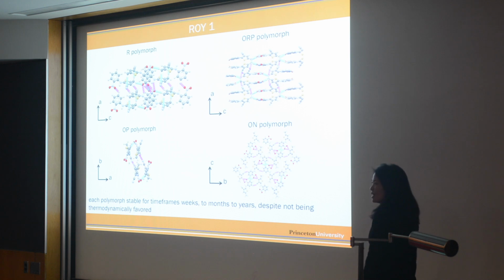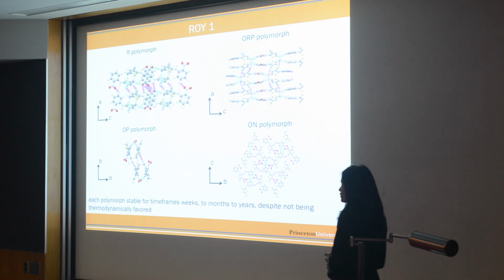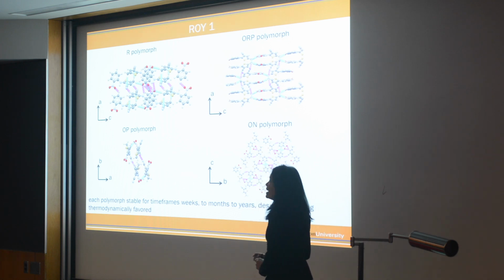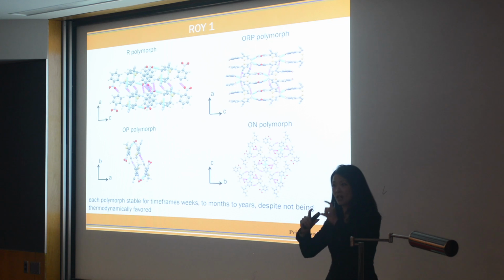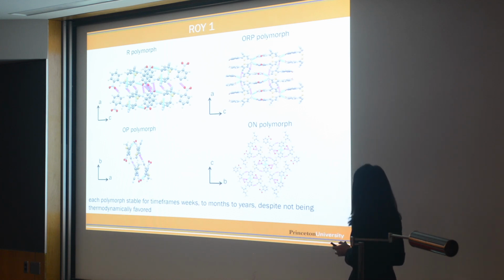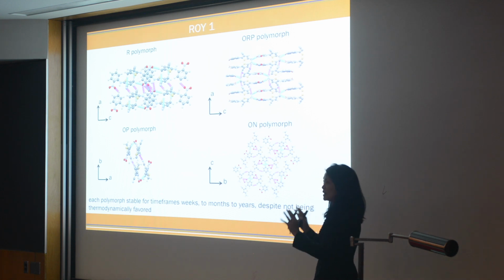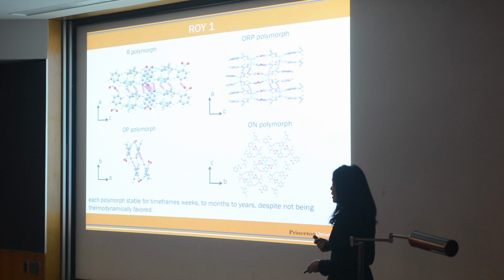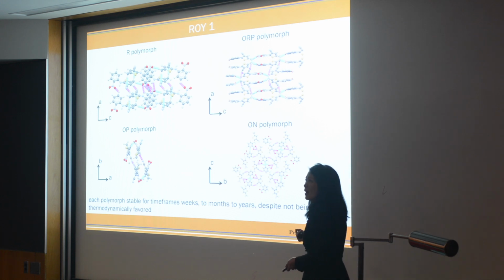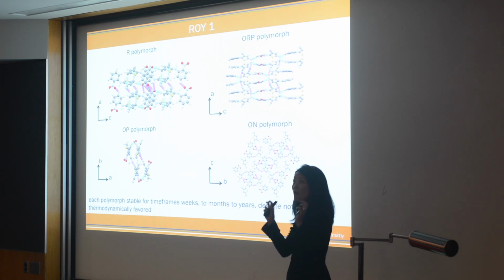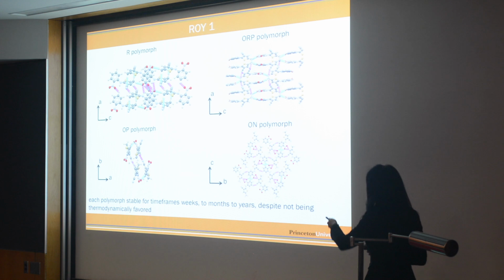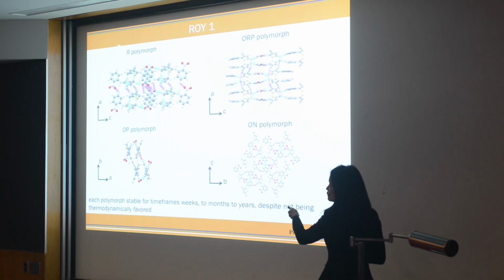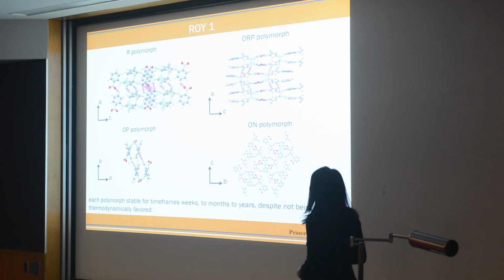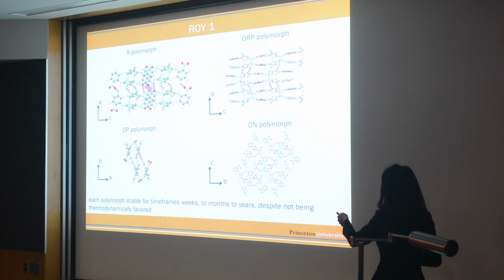Okay? This is ROY. It's a pharmaceutical compound. So ROY stands for red, orange, and yellow. Not very creative. And it turns out ROY has 2 different conformers. So the molecules can be oriented in 2 different conformations. And so ROY1 is one of the conformers. ROY1 has many different polymorphs. In fact, folks who study polymorphs really love this compound because it's quote unquote the most polymorphic compound around. So these are named, again, not too creatively. R for red polymorph. This is orange red plate polymorph, orange plate polymorph, orange needle polymorph. Okay? But there are many other polymorphs of ROY1. And if you look across ROY1's polymorphs, all of them show these interlayer short contacts.